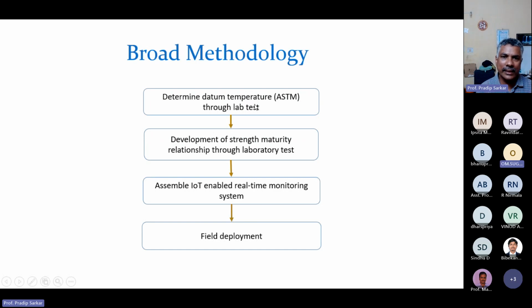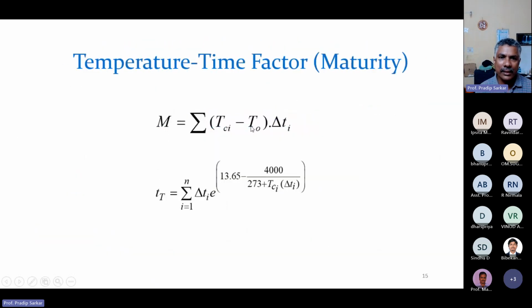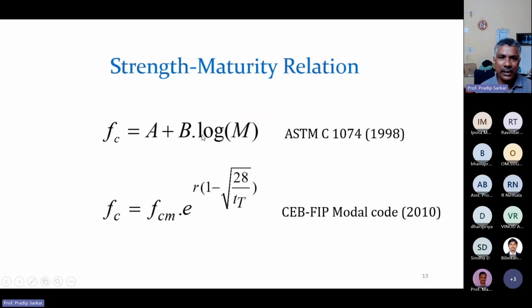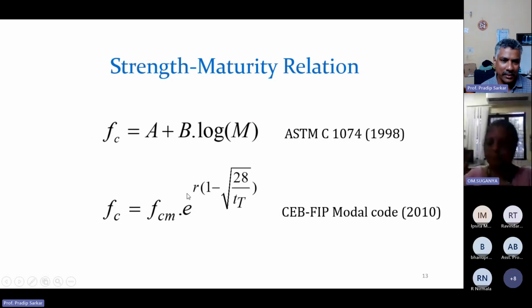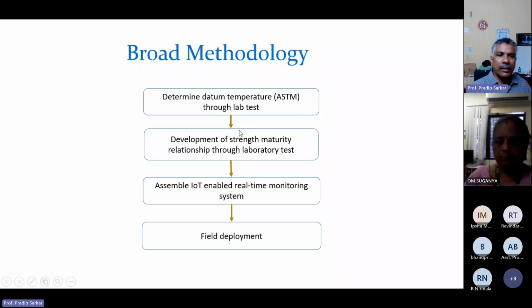Once we get the datum temperature, we can develop the strength maturity relationship, again through laboratory test, because we know T naught now. After that we can do some more tests in the laboratory. See, this is the strength maturity relationship. In the strength maturity relationship, we have to find out the constants A and B for that particular mix. So if we take the maturity and do break tests of particular specimens and make the relation using this model, we can calculate the A and B values. So we can have a relation between strength versus maturity. Once we have that relation, we assemble the IoT enabled monitoring system in the actual structure, and we feed the strength maturity relation into the system, and then we get the data in field deployment, right?